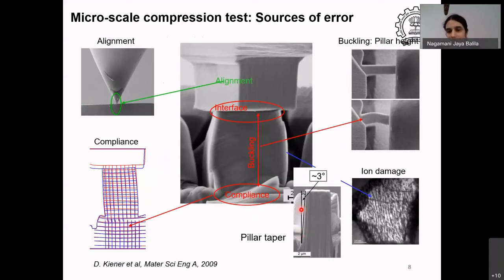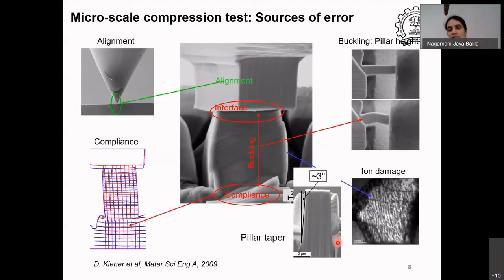The fact that the pillar is not an exact cylinder but has a taper — almost like a conical shape — raises the question: where do you measure the cross-sectional area from? Should I measure it at the top, middle, or base? Usually the material deforms in the region with the smallest cross-sectional area, so the protocol is to measure right at the top. These are parts of the experimental error.